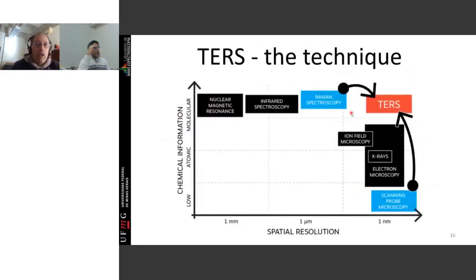This is summarized on this plot, where in this axis here I'm putting the spatial resolution. So this is millimeter, micrometer, and nanometer. So if I take a scanning probe microscope like STM, it goes down to atomic resolution, okay? But here you have some sort of level of information, okay? Raman spectroscopy can give you a lot of information, but because it's optics, you cannot cross the diffraction limit. If we are able to do what Renato Zenobi and his group did, join Raman spectroscopy with scanning probe and look into the Raman emission very close to the object, I can populate this area here where I have high resolution and high molecular information with this technique, which is called tip-enhanced Raman spectroscopy, okay?